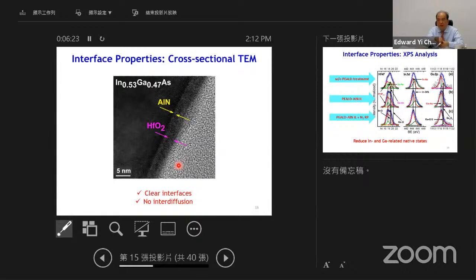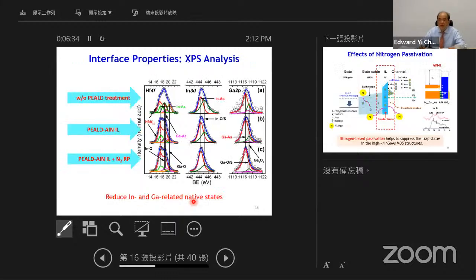Okay. And this is the TEM image of the interface. And you can see that the interface is very clear and no interdiffusion of the atoms. And then you can see that from the XPS, using this kind of PEALD treatment, all this oxide formation is reduced. Aluminum oxide, indium oxide, gallium oxide, the native state is nothing, and the amount of oxide formation is greatly reduced.